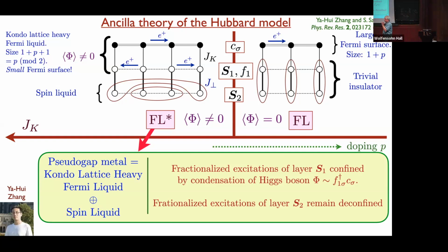Yeah, there's some m star. I can't compute it. It could be heavy because it is a Kondo lattice. So there's an m star here. We know that roughly m star is 1 over J, not 1 over t. And in fact, the value of phi determines the pseudogap in the antinodal region. So you can fit it from the data very easily. That's about 30 meV.